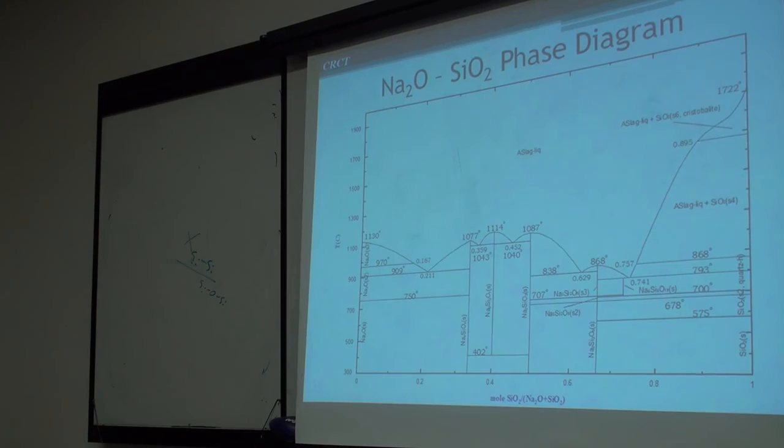There's your sodium silica phase diagram. In this case, we don't have a miscibility gap, but you can see you have a tendency to demixing, the S-shaped liquidus. If you calculate the metastable phase, if you took the solid phase out, you would find a metastable liquid-liquid miscibility gap down here.